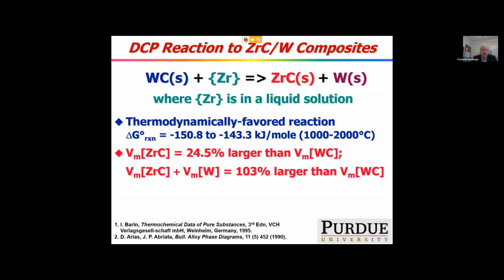What's more, the carbide we produce has a larger volume than the carbide we consume. And even more important, the combination of the two solids we produce, ZrC and tungsten, is about twice the volume of the starting tungsten carbide. So that's how we conduct the shape preservation. If we start with a 50% porous preform, you can fill the pores in with the ZrC and tungsten solid products and not have a significant change in shape or dimensions, less than 1% dimension change. That's the idea. We call it DCP because we're using a displacement reaction to compensate for the prior pore space in the preform.